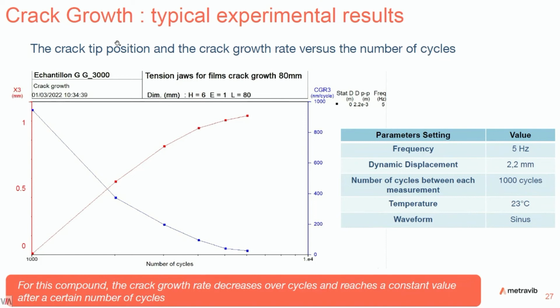First, typical experimental results: the crack tip position and the crack growth rate versus the number of cycles, for one tearing energy, 3000. The blue curve is the crack growth rate, in millimeters per cycle, and the red curve is the length of the crack as a function of the number of cycles.